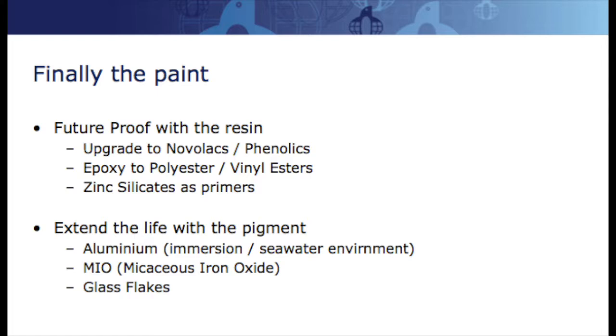Zinc silicates are, without question, if you have the right environment, the best primer you can have under the rest of your coating system. But I said, had the right environment again. Zinc, of course, by nature, is quite an expensive system, so you're increasing the cost. I wouldn't say dramatically, but there is that aspect of it. But you also need an electrolyte for a zinc silicate to work, so you have to understand, what are we trying to do here? What are we protecting against? If you're in the middle of the desert, a zinc silicate's not going to make any difference to you. It's not going to help you, unless you have a lot of humidity and condensation. So you've got to be aware of your environment before you choose the coating system.